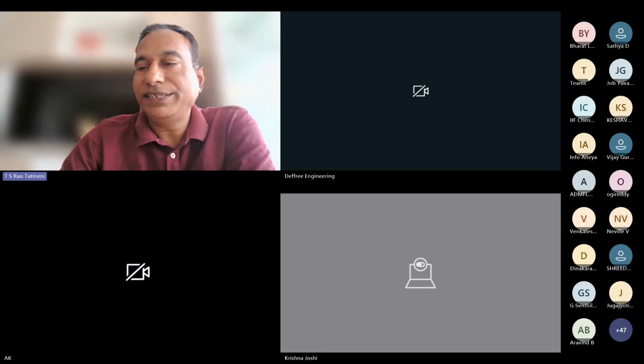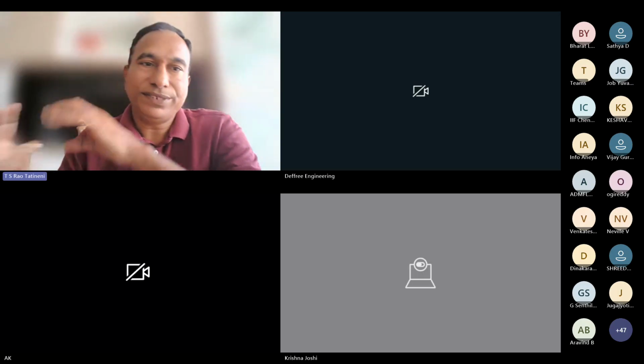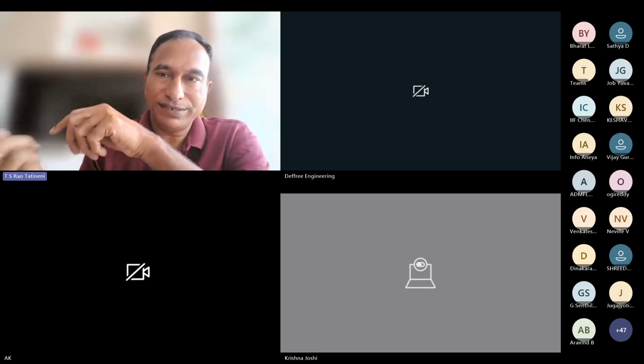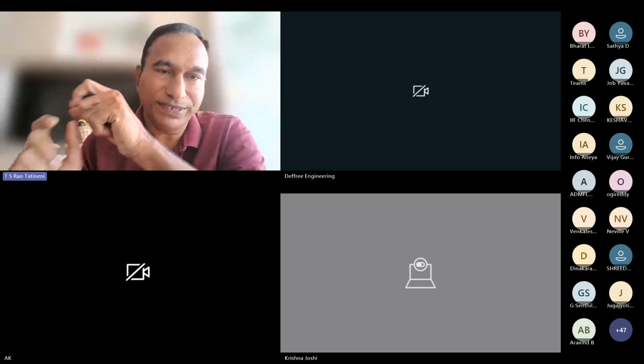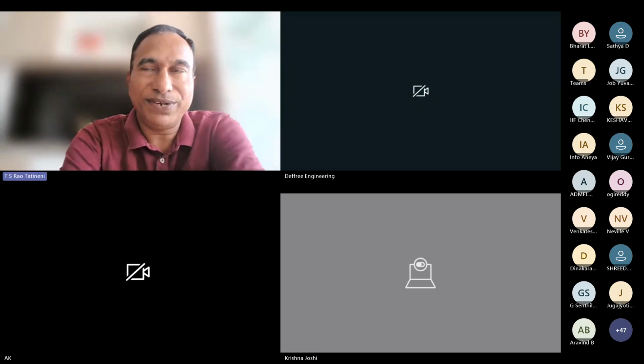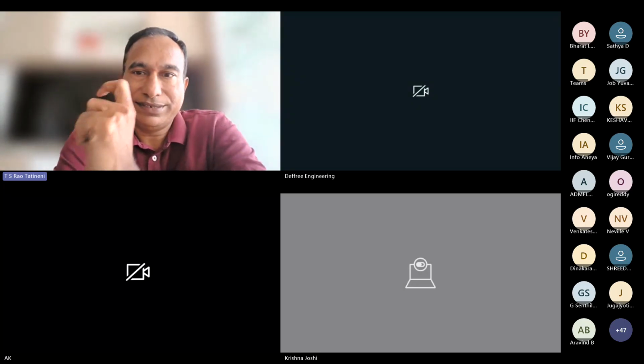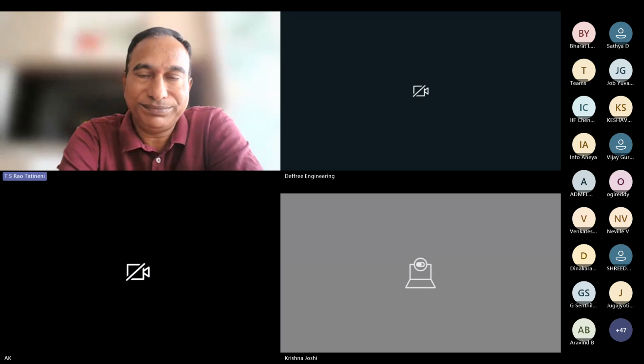There is no harm in increasing the feeder, but at the same time, you need to see the modulus of the feeder. The modulus of the feeder should not be greater than the significant modulus of the location where the feeder is connected. Otherwise, you will end up with shrinkage at the junction of the feeder.